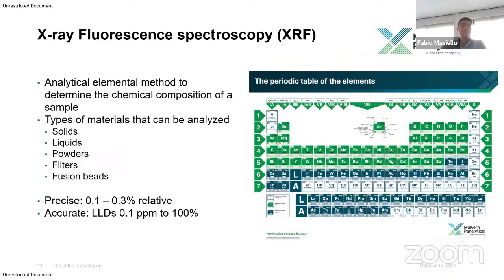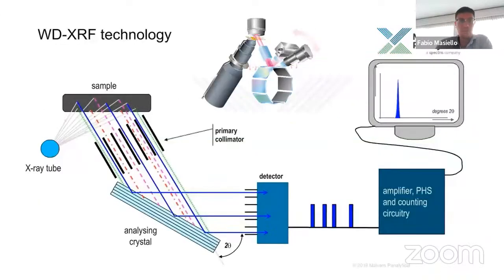X-ray fluorescence spectroscopy is a method that allows you to determine the chemical composition of a sample, so which elements are inside of my sample. The materials that can be analyzed are quite broad: solids, liquids, powders, filters, and fusion beads. It's quite a precise technique, with 0.1 to 0.3% relative accuracy, and also very accurate. You can go from a low limit of detection of 0.1 ppm up to the full 100%. That's quite a feature of the technique.